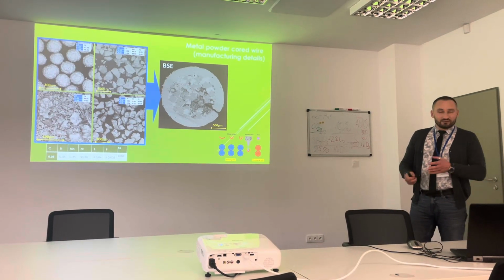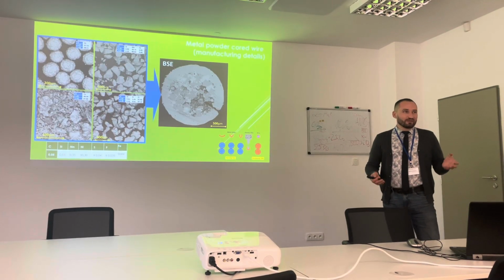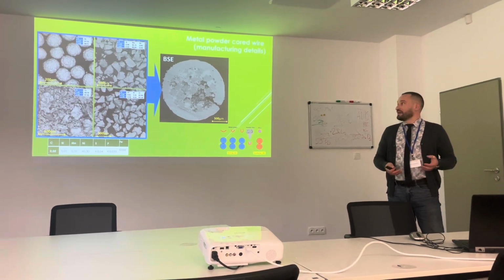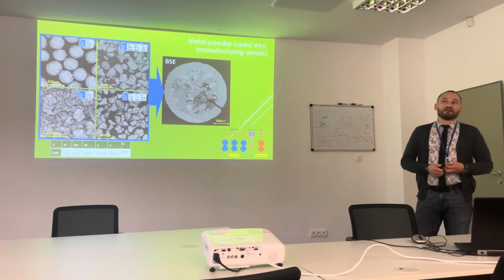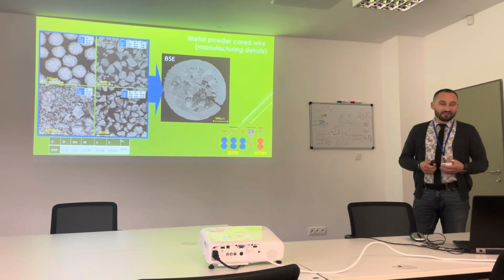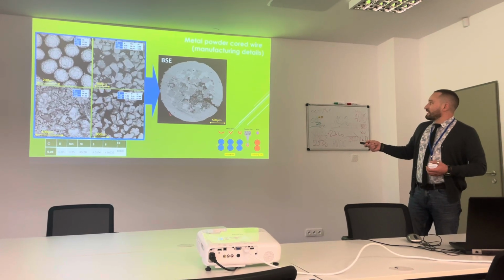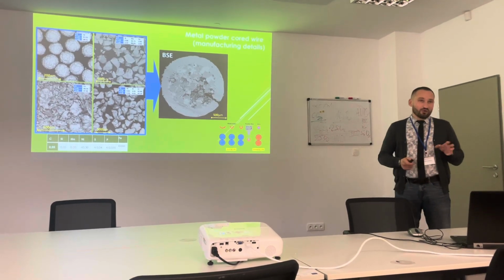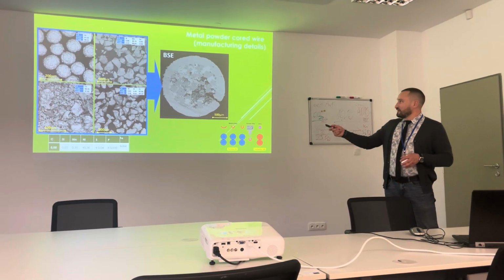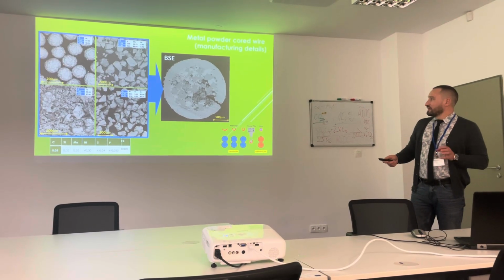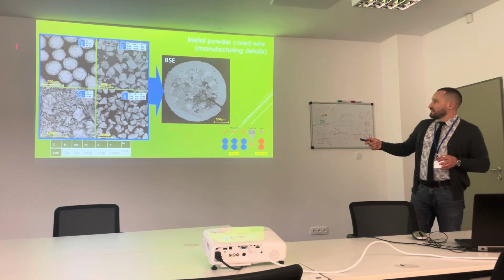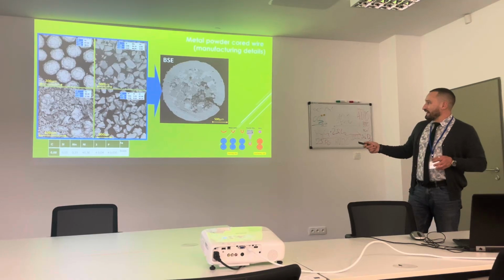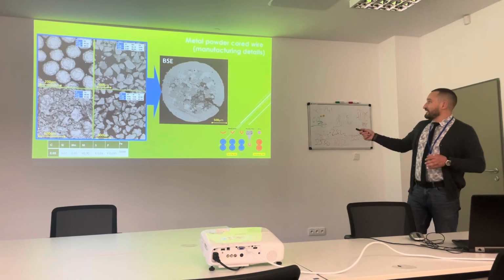Let's start from the beginning. Why arc additive manufacturing? To perform wire arc additive manufacturing, firstly you should have wire. And in our work, we suggest and invent a metal powder cored wire. What does it mean? We have a metallic shield, and inside this tube we have a mixture of pure metal powders. For example, for the classical composition, it's a nickel, cobalt, chrome, and manganese mixture inside the tube.